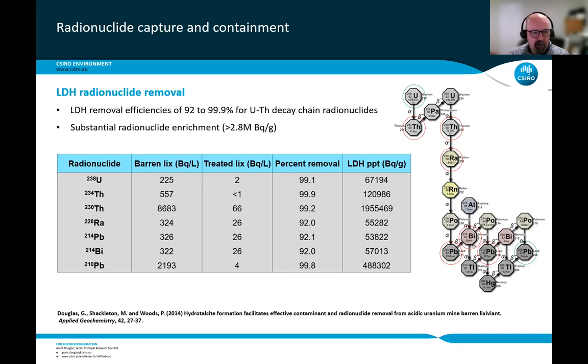Almost 2 million becquerels per gram, but aggregated, we had a radionuclide enrichment of around about 2.8 million becquerels per gram. So this is a really, really efficient getter for a whole range of radionuclides from the uranium and in fact thorium decay chains as well. And that's one of the really, really good outcomes of this research, that we were able to demonstrate that we were so efficient in actually removing a whole range of radionuclides.